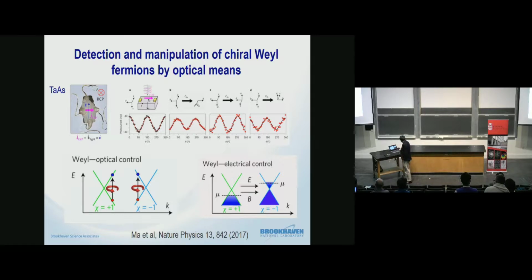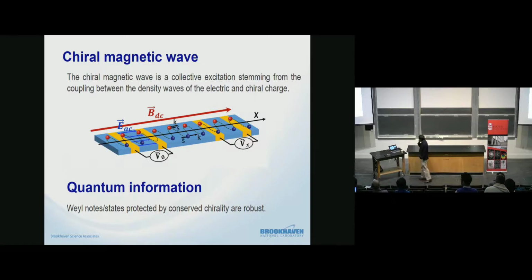So most recently, we were looking at something even more. It's the AC chiral magnetic effect. The idea is this way. Now, if you have a chiral magnetic material here, okay, and you apply the bias here, and this is the DC magnetic field along this direction. Now, E applied here is also in the same direction. Essentially, you provide a chiral source of that, right? And you also, in this field, will be able to have a charge. The right-handed one goes forward, and the left one goes on the other part of the phase over there, and it causes a charge separation.